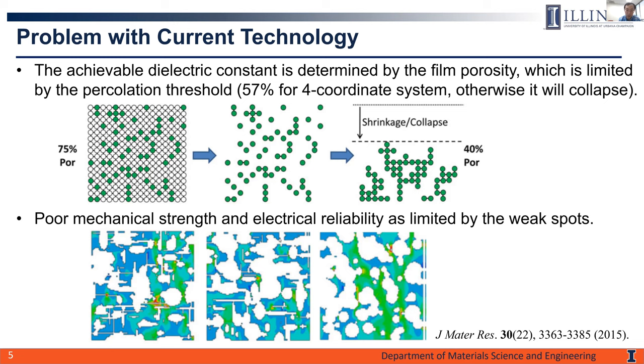And the second problem, in addition to this theoretical performance limit regarding the porosity level, is another practical concern: the mechanical strength and the electrical reliability. For these interlayer dielectrics, first of all, they must have sufficient mechanical strength because we need to make sure they're compatible with the chemical mechanical polishing, or CMP, process. And they also need very good reliability to support the product lifetime.